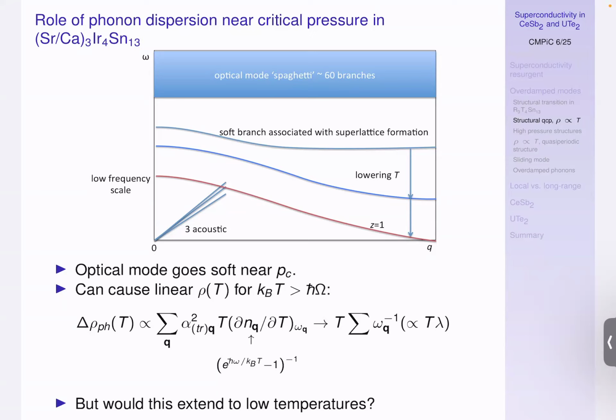If you work through the theory for scattering of electrons from phonons, you can contract a lot of integrals and complicated looking formulae into a relatively straightforward sum over phonon Q vectors, where it's always the Bose occupation number of each Q vector which matters. And that goes like 1 over e to the energy over temperature minus 1. If temperature becomes large compared to omega, then this expands out. You get basically just T linear resistivity. So that's effectively similar to the equipartition theorem. The degree to which these modes are excited is proportional to temperature, provided that the temperature is large compared to the vibration frequencies.